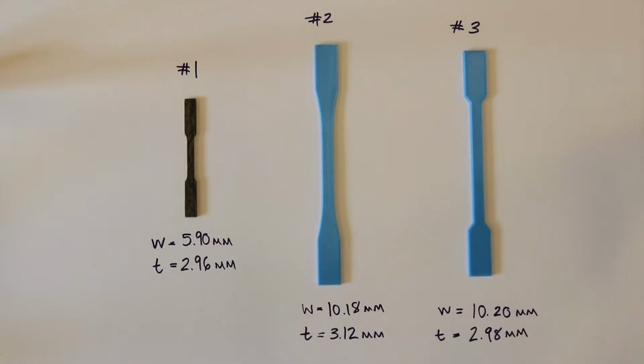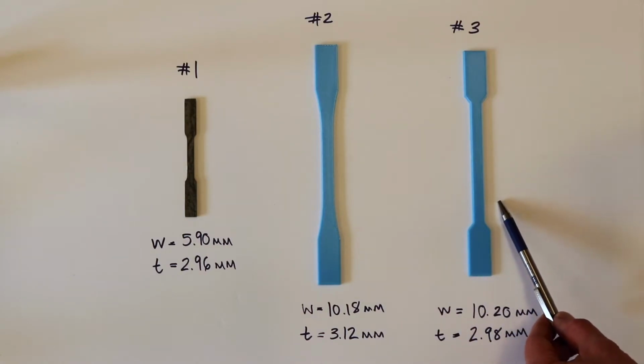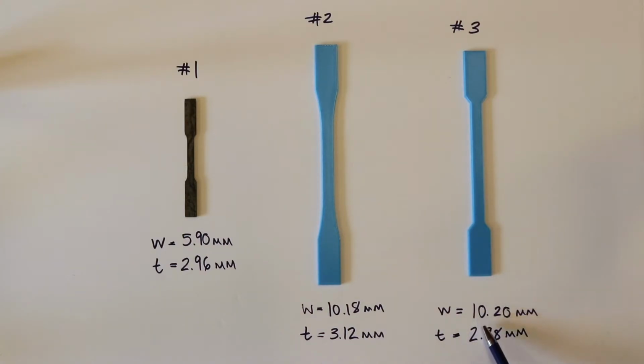Okay, so I've made the measurements of the width and thickness of each of our three samples, and you can see them written down there. So for the structural steel, width 5.90 millimeters, thickness 2.96 millimeters. For the first PLA sample, second sample out of the three, we have a width 10.18 millimeters and a thickness 3.12 millimeters. And then for our third sample, also PLA, we have a width of 10.20 millimeters and a thickness of 2.98 millimeters. So I'll get the first sample now.